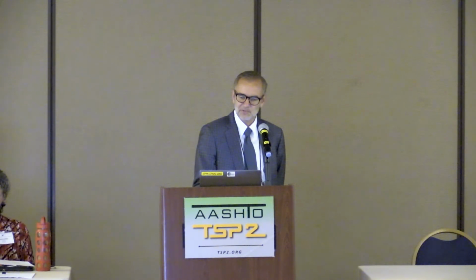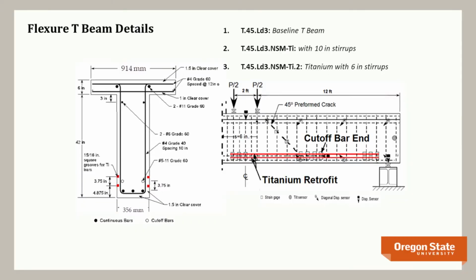For flexure, typical problem we're trying to fix here is we've got diagonal cracks in our girders, and then these are terminating around a cutoff location. And so what we're using these titanium bars essentially to act as non-contact lap splices to extend that bar closer to the support so that we can bridge over that deficiency.